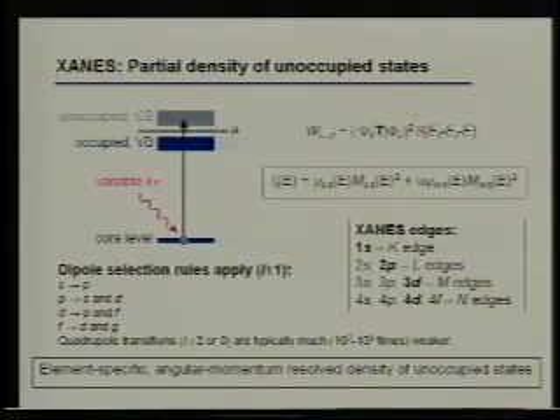So again, the XANES is dominated by the equation that I've shown at the top of the page here. This is Fermi's golden rule, and that gives the probability of transitioning from your initial state to your final state. The first term with the Hamiltonian shows the final state and the initial state. When you do the dipole approximation, you actually get selection rules that come out of solving this equation when you put in the wave function. That says if you start from a core level that's an S-like level, you can only go to angular momentum states that are plus or minus 1. So from S, you can go to P, as I've shown here.